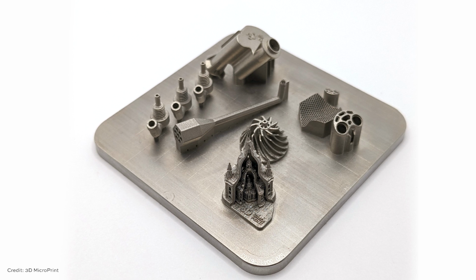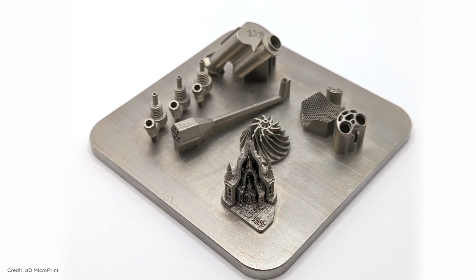So the gripper component is usually, or it's one of the printed assemblies we do, which starts at a minimum at least 5 parts. Sometimes there are 7 to 8 parts, which we print in a single process. So just leaving small gaps where you have joints or hinges and something like this therein. So the tiny gaps are somewhere between 10 and 15, 20 micron, depending on the size of the gripper or the size of the powder we are using on them.